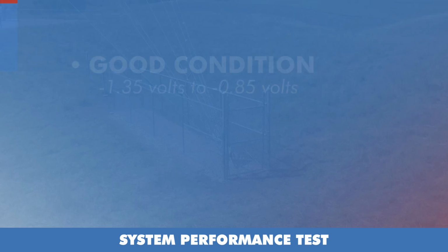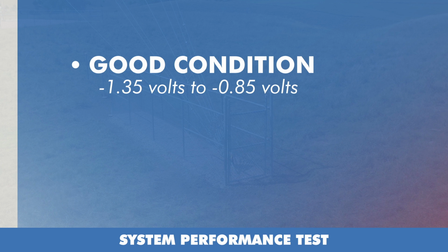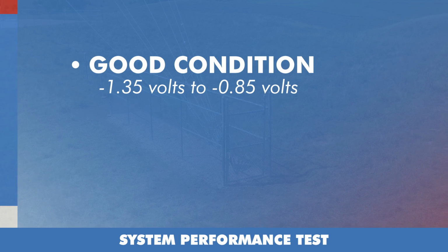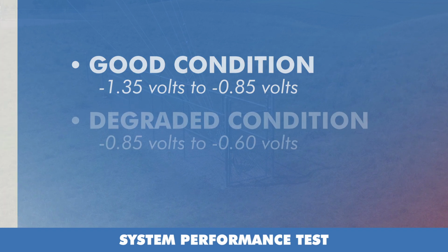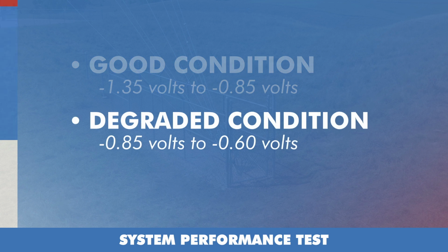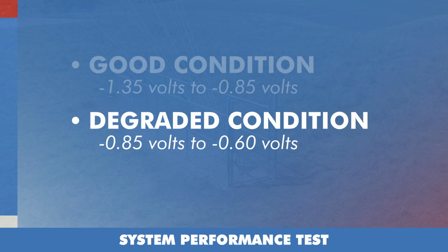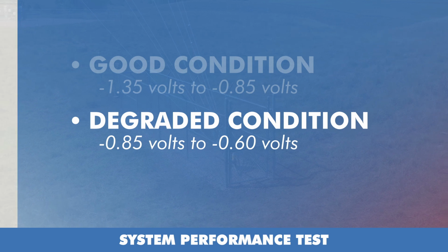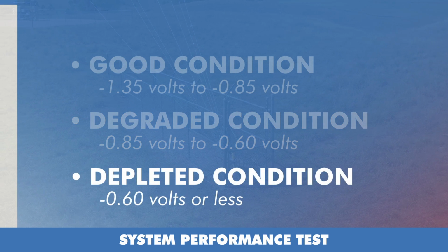A reading between negative 1.35 volts and negative 0.85 volts is normal for anodes in good condition. Readings between negative 0.85 volts and negative 0.60 volts tell us that the anodes are in a degraded state, and negative 0.60 volts or less is a sign that the anodes are depleted.